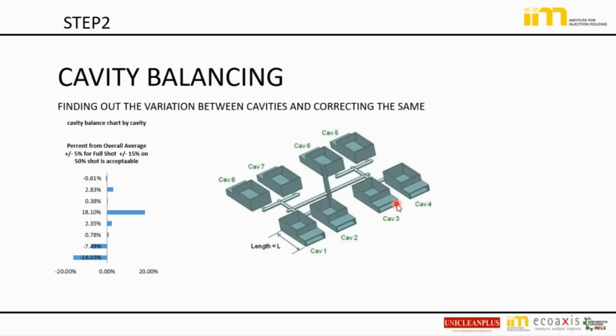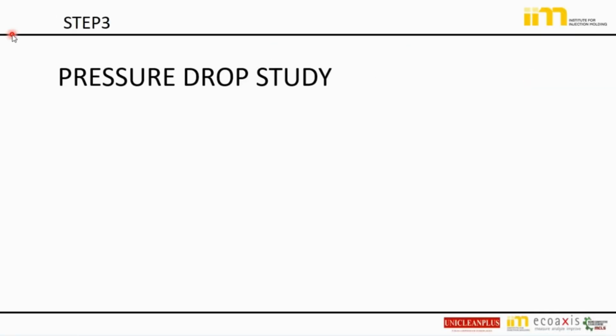And some people do it at 50% filling also, where the part will be filled only 50%. There, even a 15% difference is acceptable. Okay. If you are able to meet this, cavity to cavity consistency comes only if the steel is machined the same, the feed systems are the same, the filling pattern of all cavities is the same, and the cooling and venting of all cavities are the same. So if we are not getting any balance, we have to check for the possible reason why. This is how it will be done, and that also calls for cooling correction.